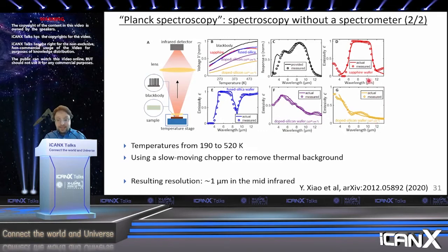And you can see that actually the results are quite good. So the solid lines over here are what we call the actual emissivity spectrum. We measure that using our Fourier transform spectrometer, like I was showing you earlier. And then the circles are what we measure using Planck spectroscopy, again, without any wavelength discriminating optics. And you can see it works quite well. Essentially across this entire range, we have a spectral resolution of about 1 micron, and we're able to pick up all of these features quite well.